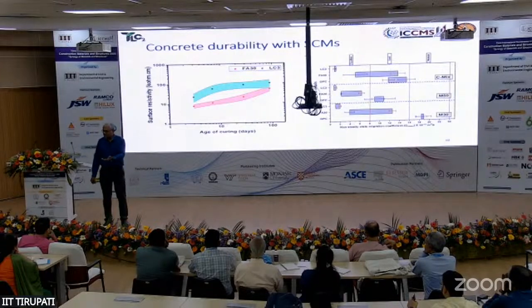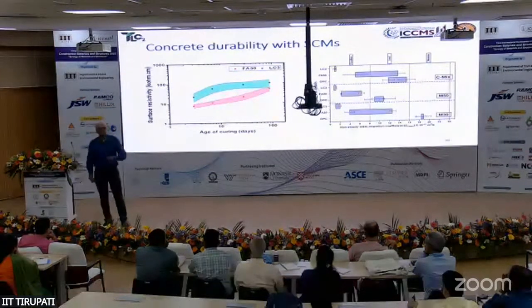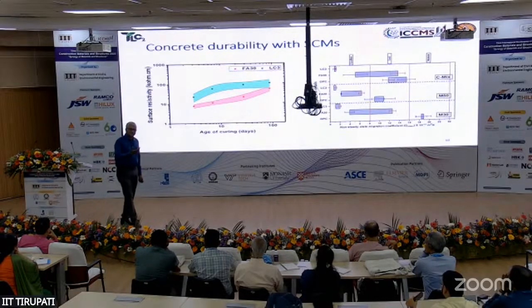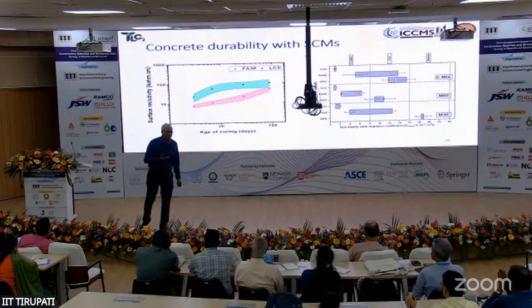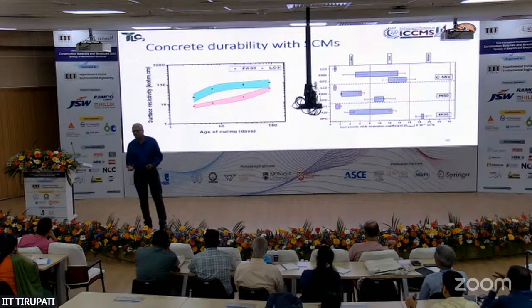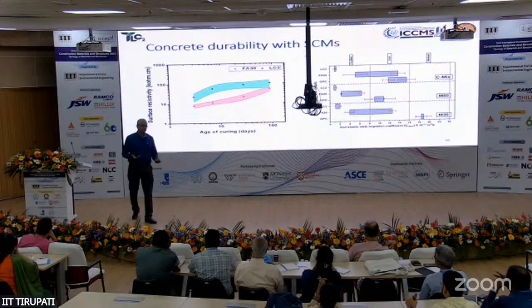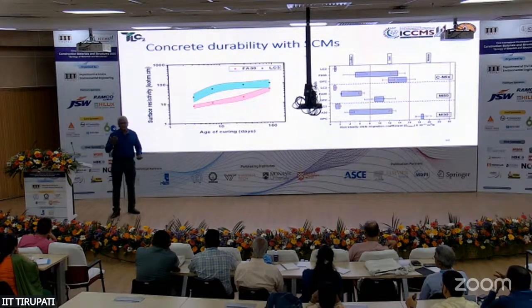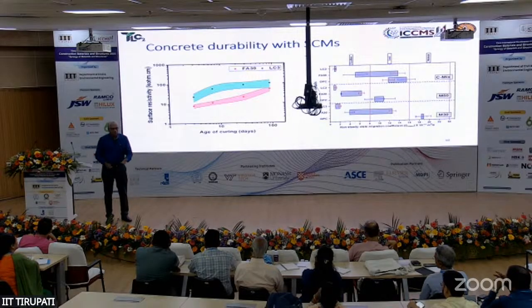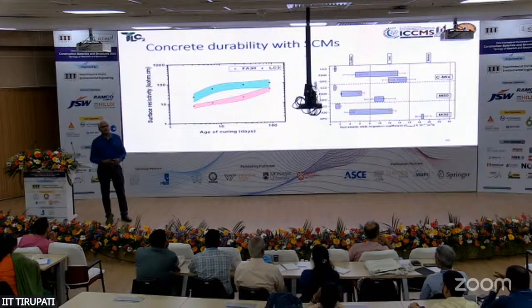And you don't always need very high structural strengths. The previous methodology of concrete design was you design for a higher strength, so you also get higher durability. But how high do you want to go in strength? Why do you want to unnecessarily keep increasing your strength, right? Your brittleness also goes up. You have a lot of other problems, autogenous shrinkage, right? All of those things can be avoided by simply looking at mineral additives to increase durability at lower levels of strength.